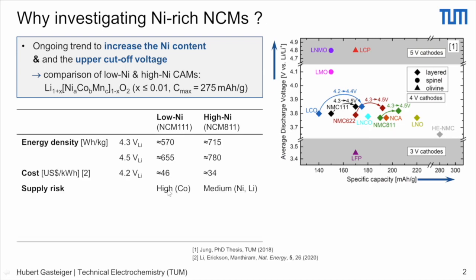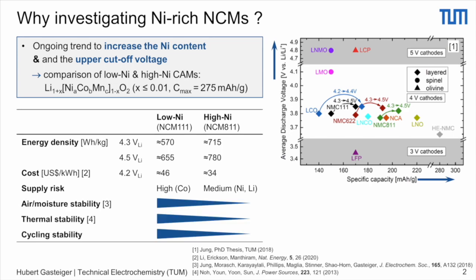So if we look at these different materials in terms of their cost, there is a paper from the Manthiram group, which looked at a potential versus lithium at 4.2 volts, and then showed that the cost of the nickel-rich materials is lower, of course, predominantly because of the reduced amount of cobalt. However, the drawbacks of these materials have to do with their higher sensitivity. So when you increase the nickel content, the stability towards the ambient, towards moisture specifically, decreases. Also the thermal stability decreases.